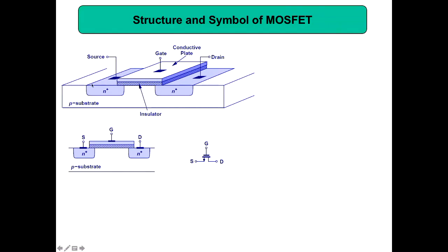And then when you connect something to the semiconductor, there is a problem. If you try to solder directly a metal, you can't solder properly. There are technologies which will enable you to solder, but then there is an issue, what is called a Schottky diode. When you have a metal and semiconductor, that will form a Schottky junction. Because of that, in the chip, when a metal is connecting directly to a semiconductor, they dope it with N plus and then they connect the metal.